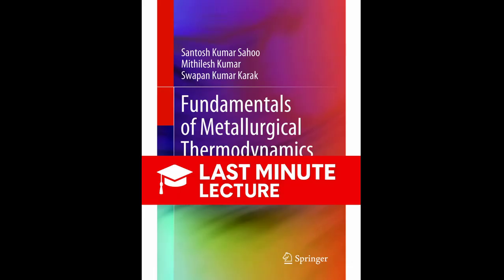And then number 4, the gold standard, constant T and P. This is governed by Gibbs Free Energy, G. The equilibrium condition is dG equals 0, and a natural spontaneous process proceeds only if dG is less than 0. And when we talk about feasibility in metallurgy, we almost always default to the Gibbs Free Energy criteria. Why is that? Well, because the vast majority of refining, alloying, casting, and heat treatment is done under constant atmospheric pressure in a controlled temperature environment, whether that's 300 Kelvin or 2000 Kelvin.